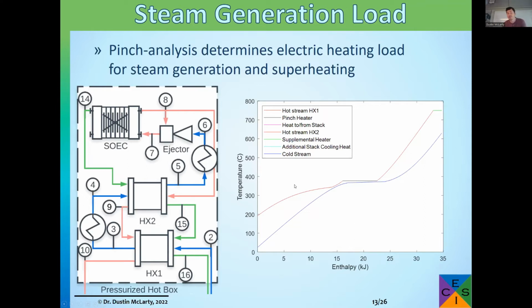So for one particular condition, this is just showing how we need the red line to stay above the blue line within 10 degrees, whatever our minimum pinch point is for the heat exchanger design. And we need to define the amount of heating we would need from these two heaters to get the supply water up to the appropriate temperature without these lines crossing.